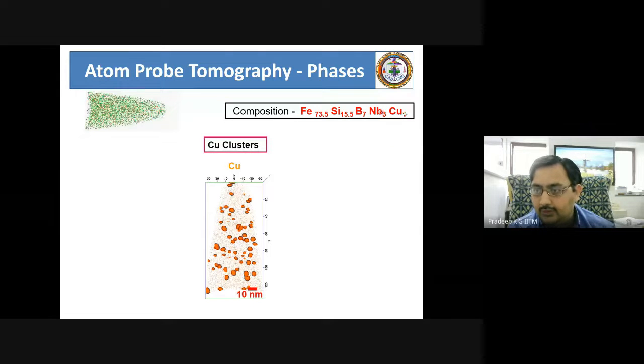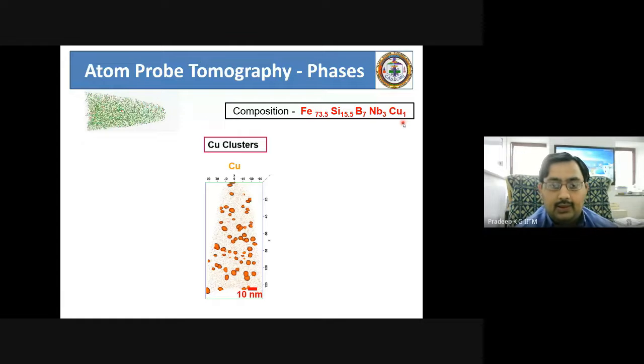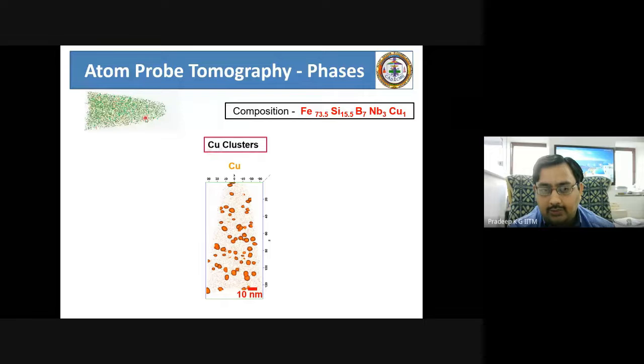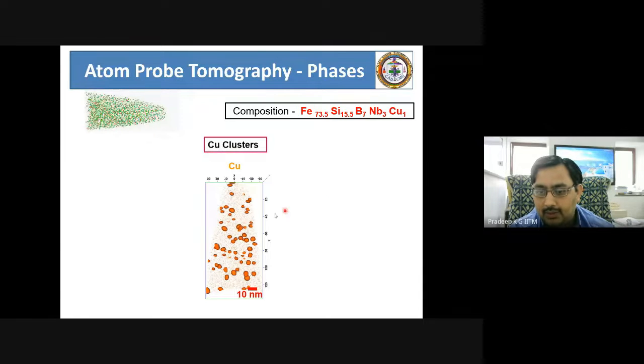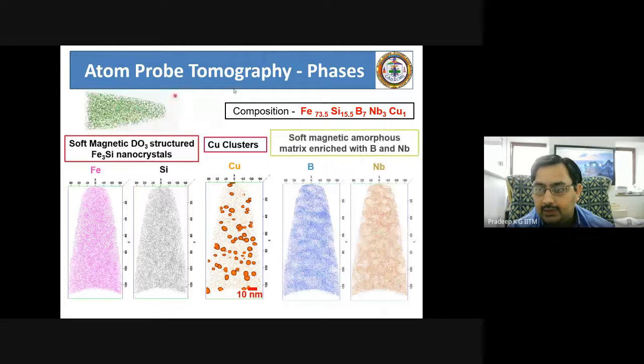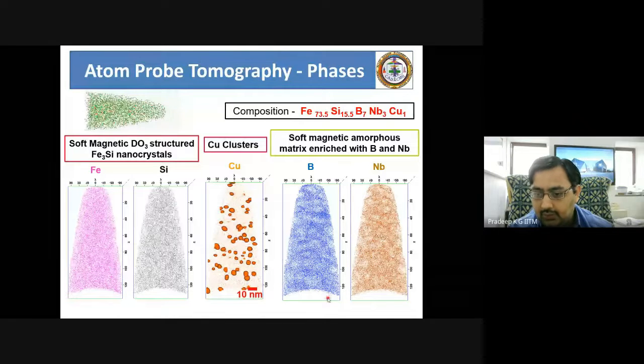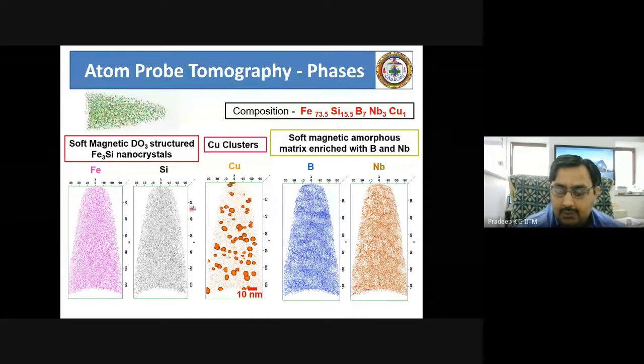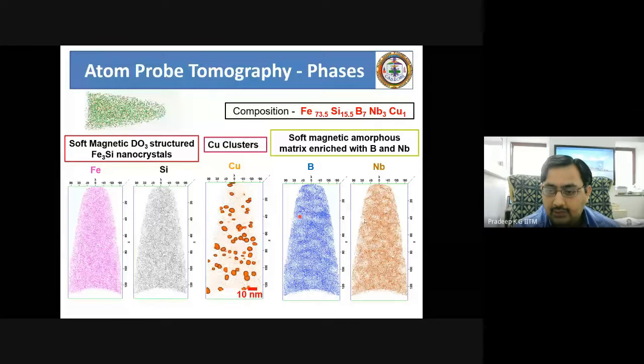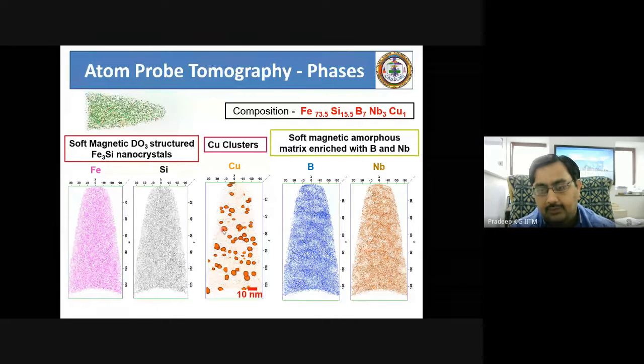As you notice, there's 1 atomic percent copper, which is usually difficult to even identify using any conventional microscopy or conventional chemical detection methods, but it can be looked into with atom probe in 3 dimensions, and you can see this 1 atomic percent copper has started forming clusters of 3-dimensional objects randomly distributed in the matrix. Now, if you similarly look at the other elements within this material, they are all preferentially segregated at different locations in a 3D volume, and all these length scales are there. What you see here is all in nanometers. That means at the nanometer scale, there is a lot of chemical heterogeneity happening, and all this heterogeneity influences your property in a much bigger way.